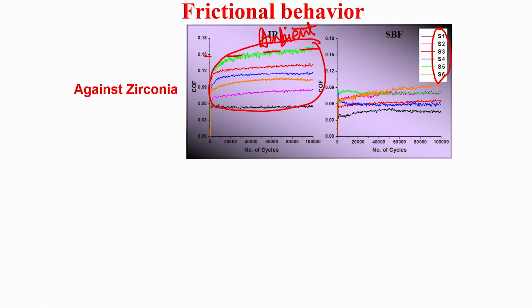So what you see here is that all these S1 to S6 materials are the flat materials, and your ball is either alumina or zirconia - this is your counterbody ball material. For all these materials, clearly from ambient to SBF there is a reduction in coefficient of friction.